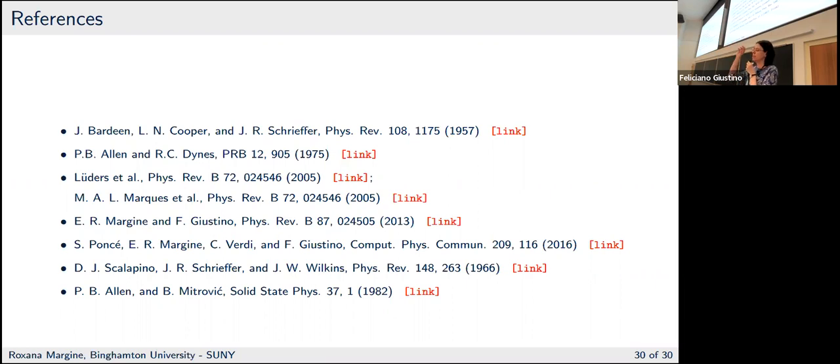And what I want to say is the difference in the two gaps will be related to how strongly the electrons couple to the sigma band and how strongly they couple to the pi band. So one thing that makes this lithium boron compound have a lower TC than MgB2 is that it's lacking coupling from the pi states. Yeah, I forgot to mention that.